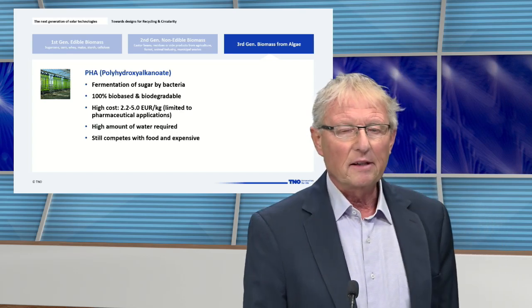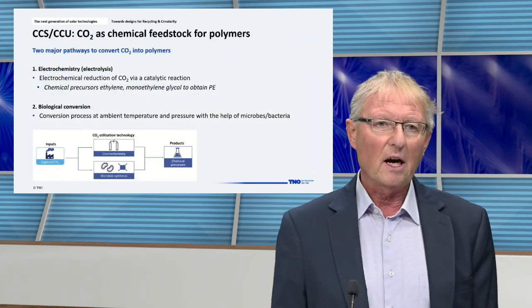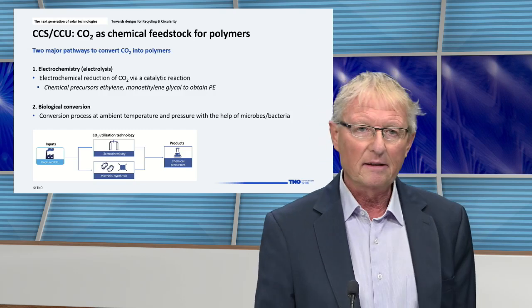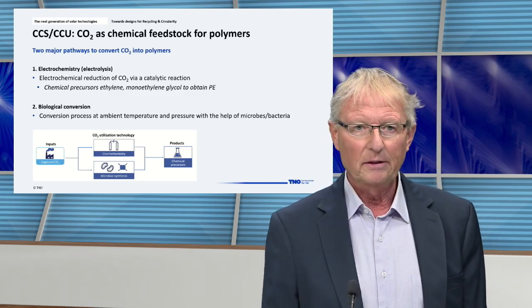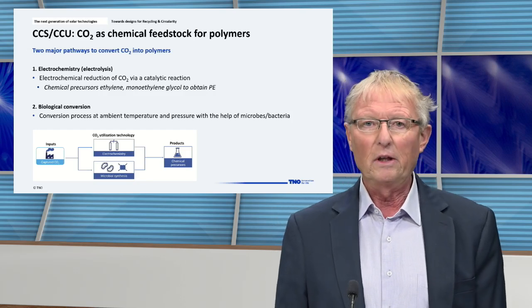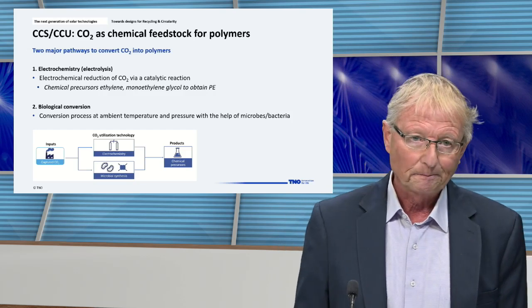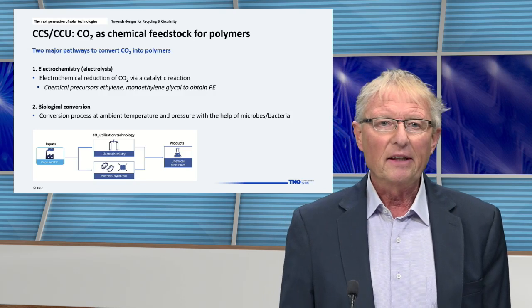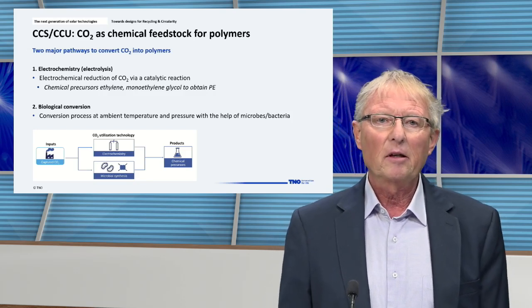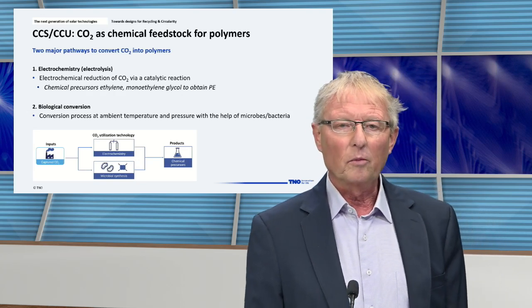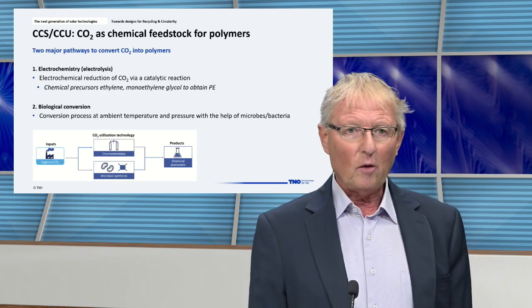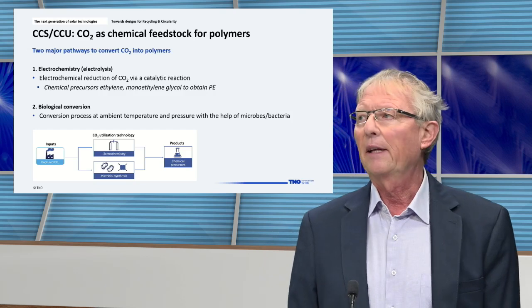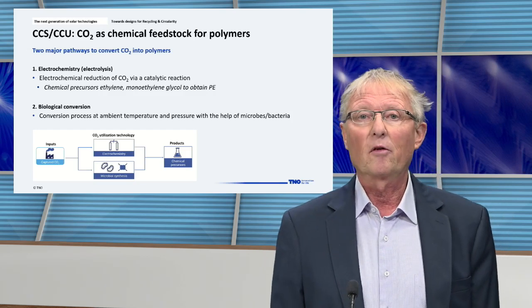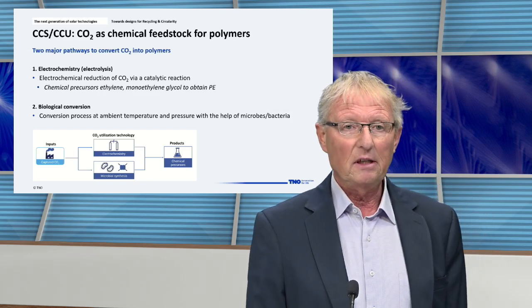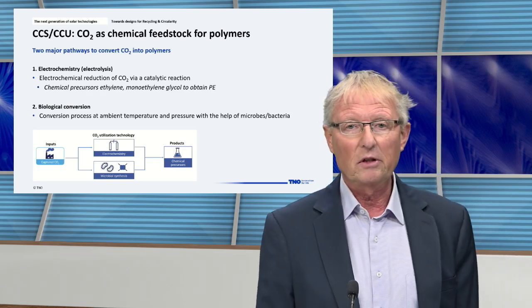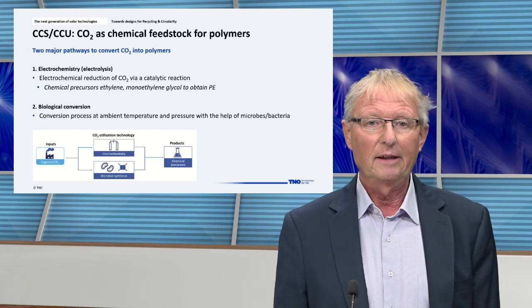If you take a look at the energy balance and the efficiency, it might be a better way to use carbon capture stored and carbon capture utilized CO2 as a chemical feedstock for the polymers. There are 2 major pathways to convert this CO2 into polymers. The first one is electrochemistry. That goes by a catalytic reaction, and the key is ethylene. So it takes this chemical precursor, ethylene or monoethylene glycol, to obtain the polyethylene. There's a second option, that is a biological conversion that's done at ambient temperature and pressure with the help of microbes and bacteria. But if it comes to efficiency, it would be better to choose the first one, the electrochemistry, specifically if it is powered by solar energy.